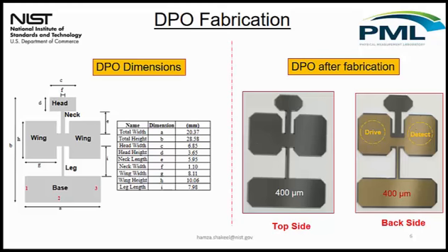On the left side, we have fabricated devices. Even though we have a rectangular feature for all of these wings, head, and foot, what we get after etching is that some of these convex corners get under etched. So we are trying to avoid this in our next design.